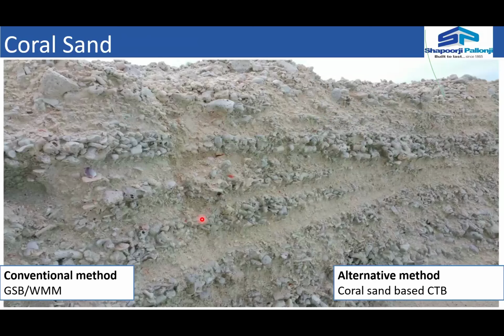So this is the section of the coral sand which is available in that particular region. When you dig around, this is giving you an indication that it is a mixture of the fine and the coarser materials, and the only thing is that it needs to be processed in such a way that it will become suitable for either my GSB or WMM layer. So what we have done is that the mix of the cement treated base was introduced with coral sand, to see what exactly the properties are and how this is meeting my requirement.